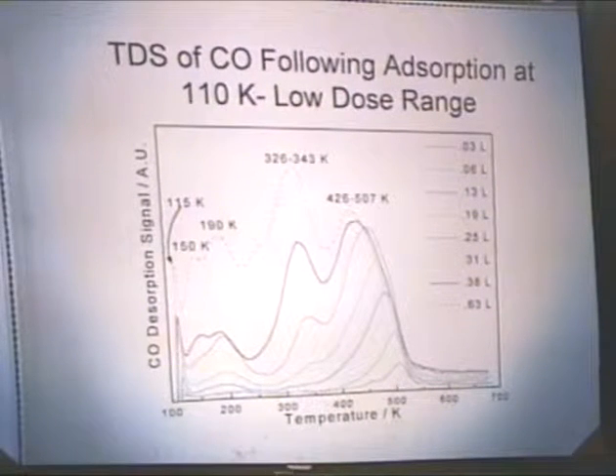For the 2 states above room temperature, you see that there's a shift to lower peak temperatures with increasing coverage. And in particular, if you look at this highest temperature state, this behavior of the shift in peak temperature is characteristic of a second order desorption. However, if you look at the peak shapes, you see that this high temperature peak is asymmetric. And of course, this is characteristic of a first order desorption. So there appears to be a contradiction in the observations, and I'll come back to that in a minute.